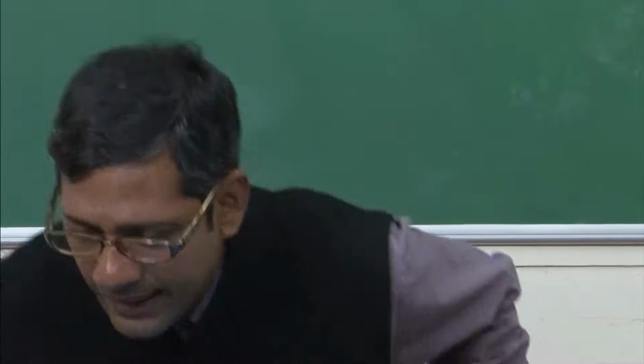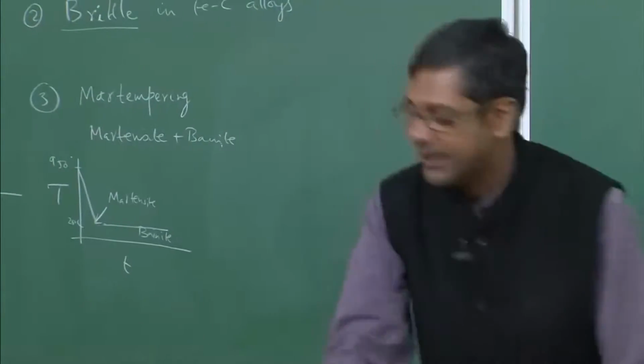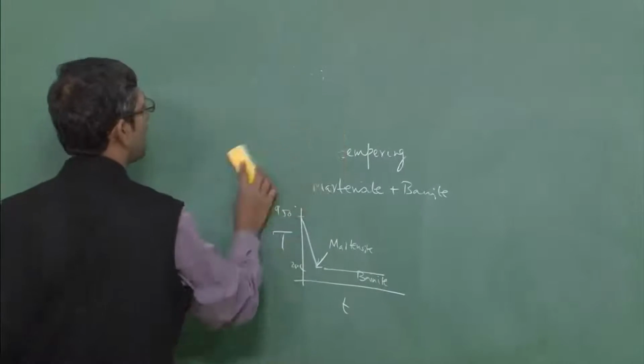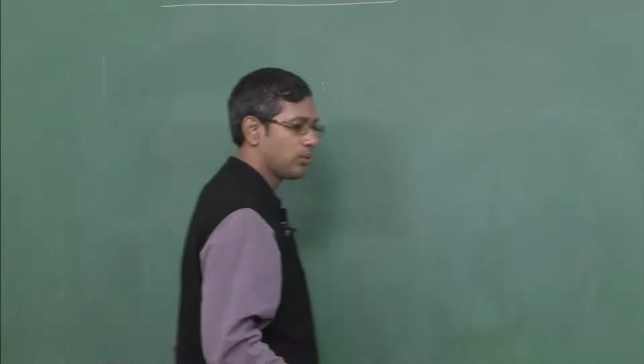So, most of the Martensites you find in the plain carbon steel must be heat treated until stage 2 to 3, that is up to 350 degrees Celsius temperature, but stage 4 is optional, as I told you. So, this in a nutshell is what you should remember. Now I am going to write down what happens on the board, so that you do not forget, and I also do not forget, and then close this chapter on Martensites. So, tempering of Martensites is done at different stages, as I told you, as a function of temperature.